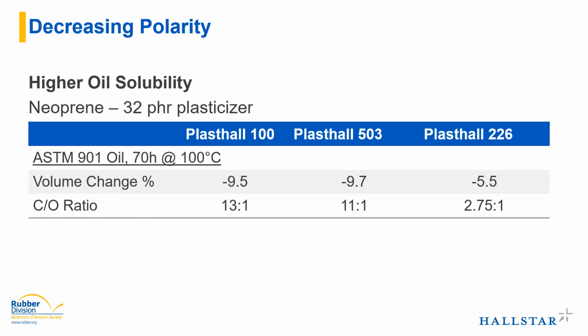And then just to illustrate with actual data, the changing of the carbon to oxygen ratio, the changing of the polarity, and their compatibility with an oil. The ASTM 901 oil is an extracting oil, so you usually see a weight loss over time after aging in this oil. And with the two first materials with a very high carbon to oxygen ratio, meaning very low polarity, you see an almost 10% weight loss. Whereas with the material on the right, in a very low ratio, so high polarity, you see much less of a volume change, meaning that less has been extracted out because it's less compatible with the oil.